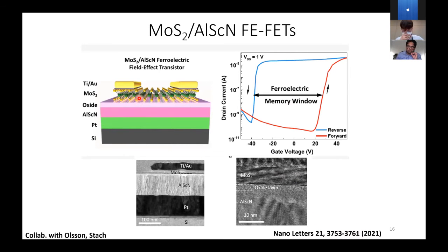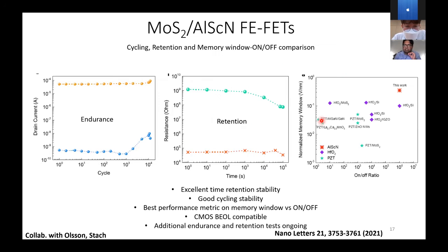We put MoS2 on top of aluminum scandium nitride grown on platinum, which is grown on silicon. All of the processes involved over here are 350 degrees Celsius. So it is in the back end of the line budget. And you can see that the transfer characteristics are very nice, almost nearly square shape hysteresis loop, and it is a counterclockwise hysteresis loop, which again tells you that it is ferroelectric in nature, right?